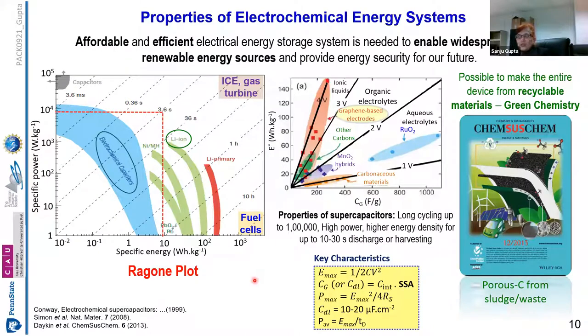Then when we look at the properties of these electrochemical energy systems, they are assessed on an industrial scale through what we call the Ragone plot, which is nothing but specific power density versus specific energy density. As you can see here, I'm focusing on lithium ion batteries and supercapacitors, or electrochemical capacitors. Electrochemical capacitors have a higher power density, unlike the lithium ion battery, which has a higher specific energy density. So why not make the best of both worlds? In other words, we need devices which lie along the diagonal around here, and can have a higher power density as well as a higher energy density.